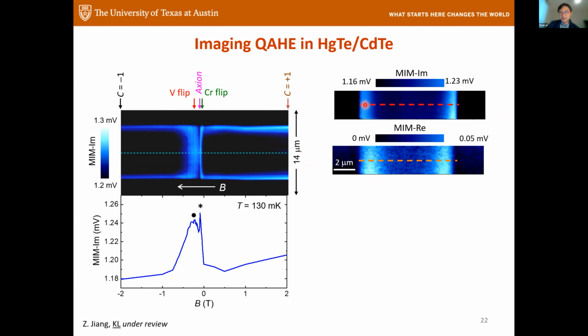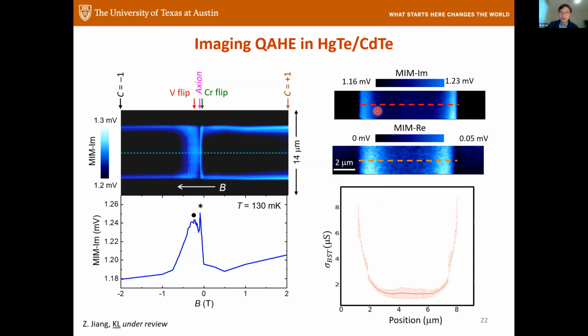But it's not just us. I believe some earlier work from Stanford also shows very broad edge states, even though theory tells us the edge should be atomically sharp, maybe a couple of unit cells. From this we can actually simulate the distribution of the conductivity, and beyond this our signal saturates.